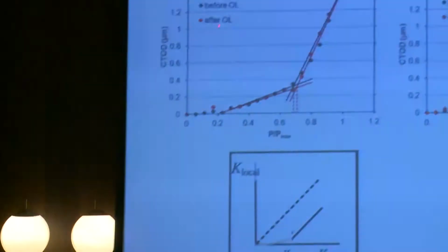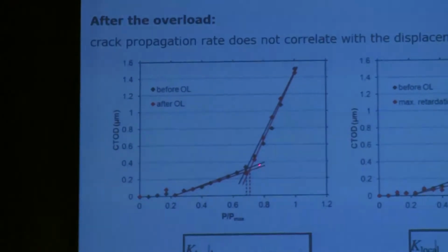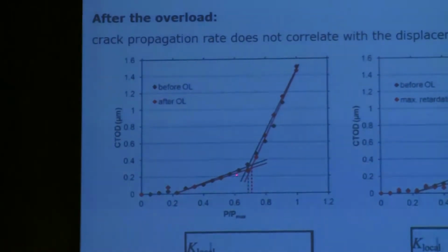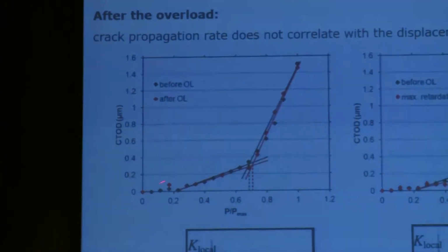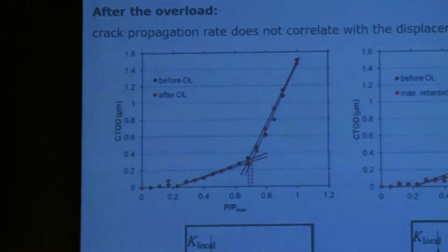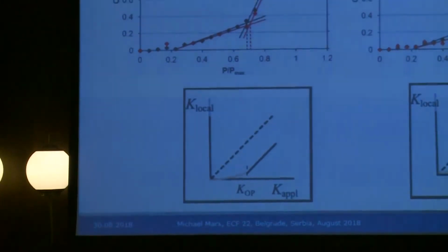And this is immediately after the overload. You see nearly no influence. You have here this part where the crack is more or less closed, and then the crack opens. So this here is the part, if you remember, on the plasticity-induced crack closure as you had it before. And this is at the position of the maximum retardation.